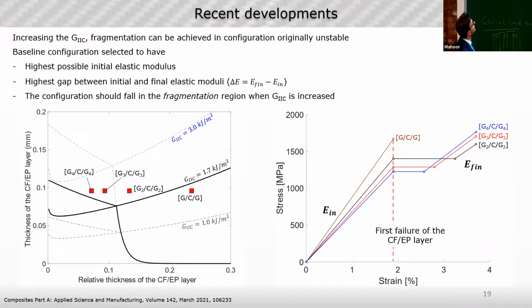So it could be summarized in a flow chart, which is quite easy to understand. And from the point of view of the fracture toughness, as I said, the fragmentation-based pseudo-ductility is easier to achieve when we employ thin plies. But using thin plies, we lose the possibility to have a high stiffness of the material at the beginning of the first stage. So as you can see here, I tried with some analytical predictions to change the thickness of the material, and of course, increasing the thickness of the glass, we lose the potential of the carbon, and of course that's not convenient at all.